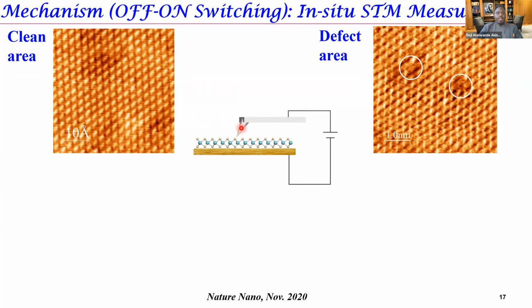The idea then is—we had a hypothesis that defects were playing a role. So we said, okay, let's image the MoS2 material, find clean areas like this, and find areas that have defects. These defects here are sulfur vacancies. And then we said, okay, why don't we now use the nanoscale resolution of the STM tip, sub-nanometer in this particular case, and park it in the clean region and do transport.